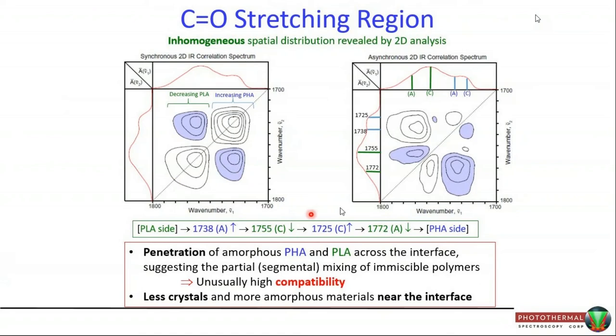Asynchronous spectrum gives you a lot more detailed picture, which is very interesting. By going through each cross peak, actually we can make the following assertion. By moving from the PLA-rich side of the laminate to the PHA-rich side, we can see initially the sudden increase of the amorphous component of PHA. We start observing the presence of the amorphous component of PHA,